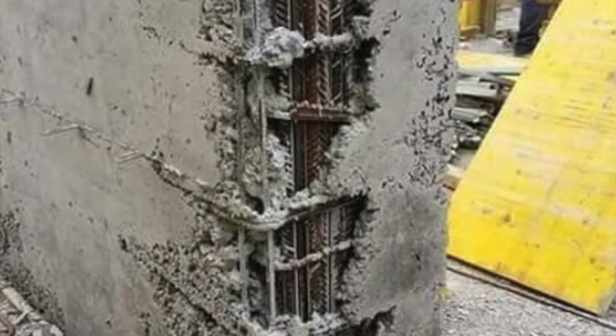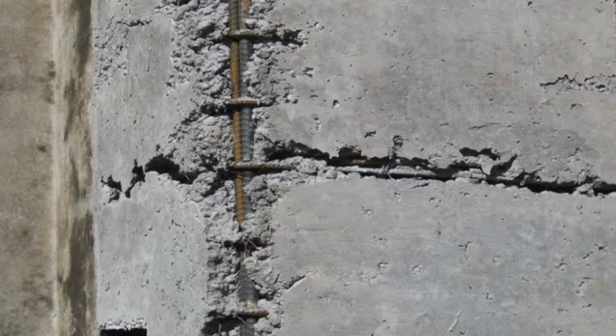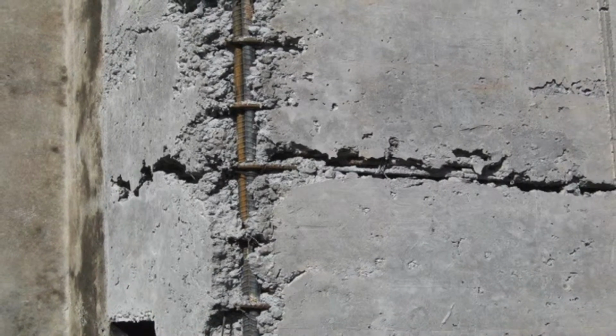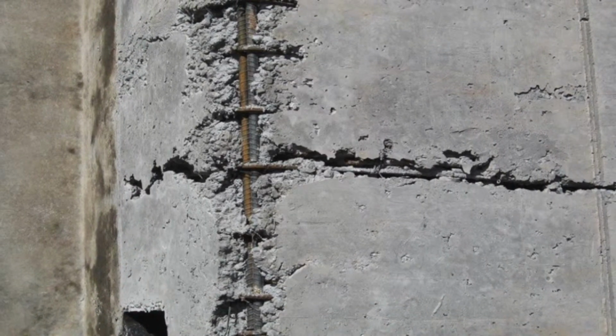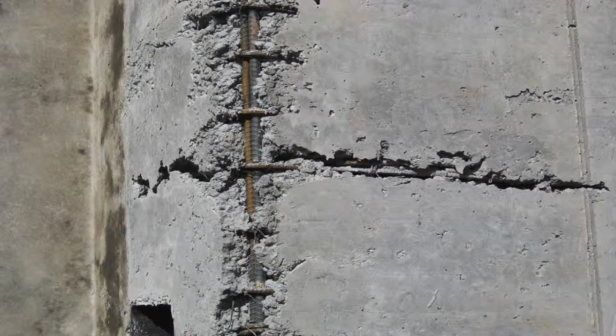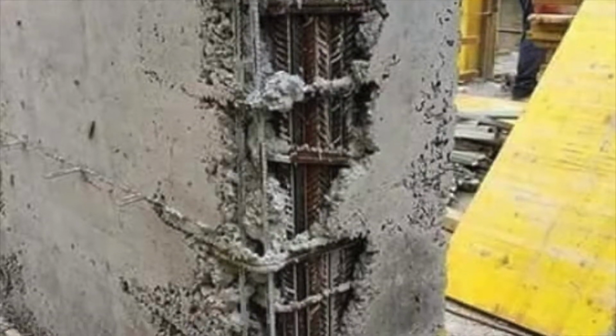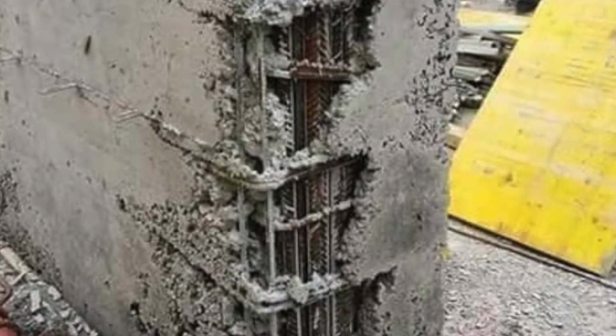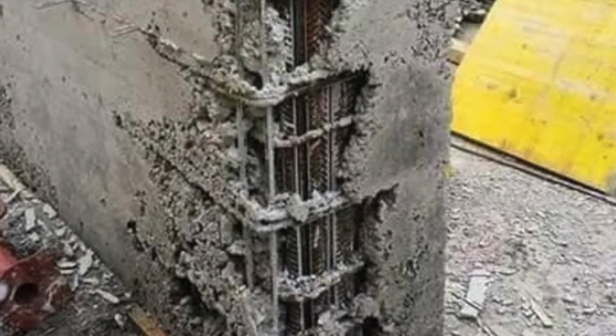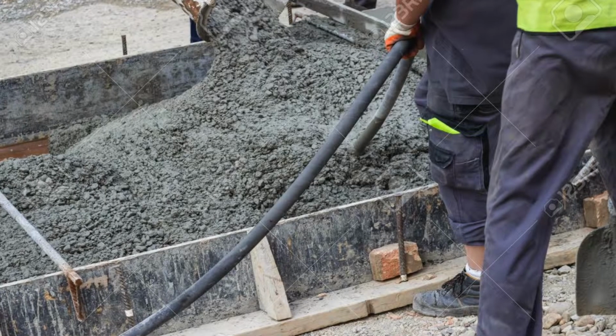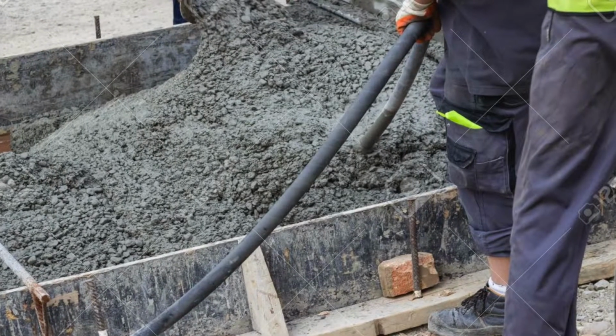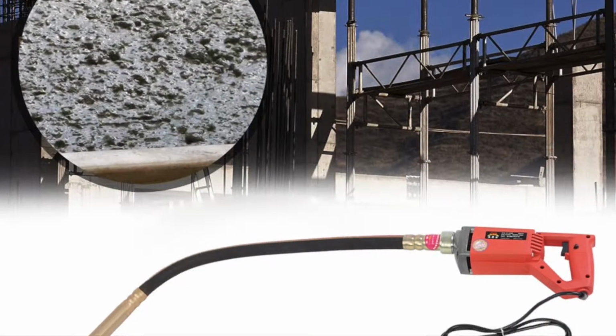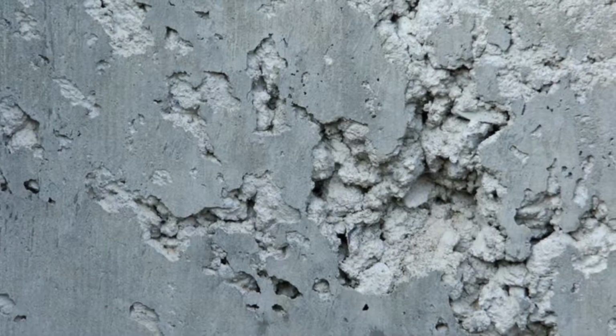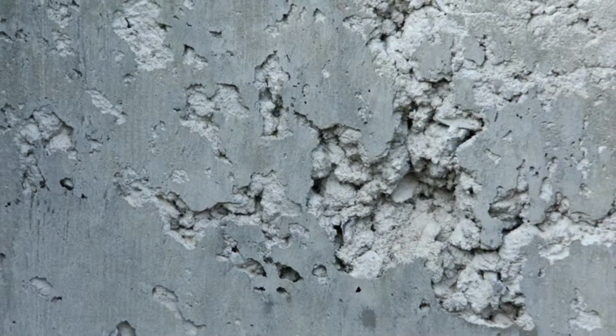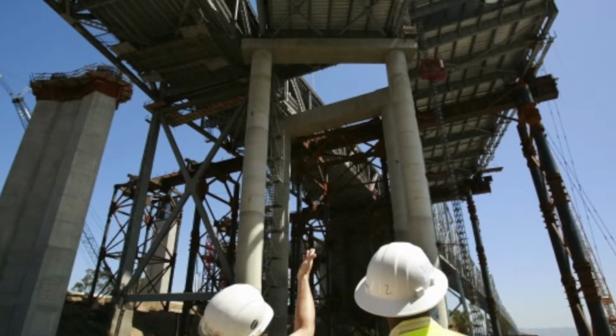And this is especially near the surface of the structure or of the formwork, where air has been trapped during pouring. This kind of air content is not desired and weakens the concrete itself. The challenge, however, is that it is laborious and takes time to remove most of the trapped air by mere vibration, and moreover, improper or inadequate vibration can lead to undetected problems much later on in the service life of the concrete structure. It's actually difficult to vibrate some complex forms of concrete structures.